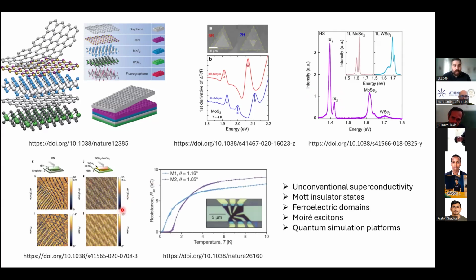And this is a very interesting group. Moiré is a word that describes a large interference. So what happens is that you stack some materials together in certain conditions and you get an interference in their crystal lattice. And this led to new properties also, like superconductivity, Mott insulator states, ferroelectric domains, and excitons trapped in moiré potentials. And these moiré materials can be excellent platforms for quantum simulation, studying the Hubbard model or similar things. The most famous one is magic angle twisted bilayer graphene, where we can see vanishing resistance. We can see superconductivity in this material.